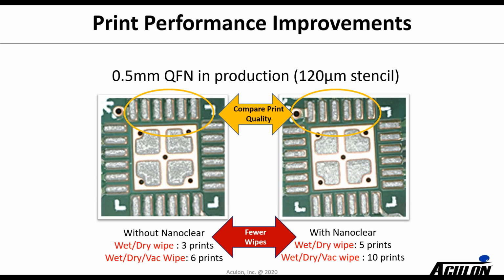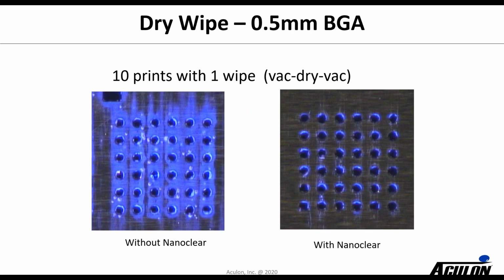Here's another example from a 0.5 millimeter QFN. And again, on the right-hand side, you can see much crisper looking shapes and deposits. And in this case, you'll see down below that we've extended the print cycle from 3 prints to now 5 prints. And that's a wet-dry wipe system. If you're doing the wet-dry vac wipe system, it went from 6 to 10 prints. So obviously, you're getting a significant amount of improvement in throughput because you've got less downtime and you've got better quality going on your printing process.